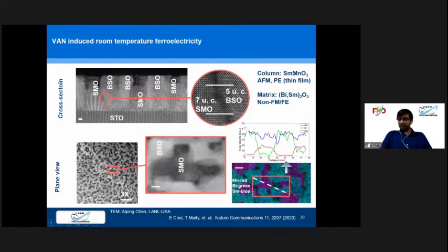As you can see, the structure is different. The reason is, if we choose a similar structure, then they will start mixing with each other. And this material does not have any ferromagnetic or ferroelectric property. So this is just a blank material, but we will use its lattice constant and elastic constant to create a pressure on samarium manganese oxide.